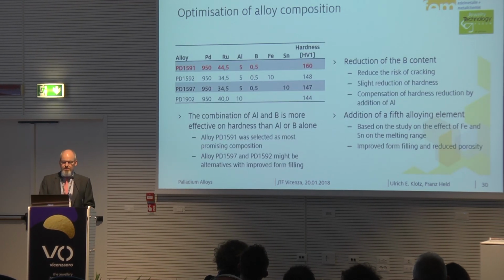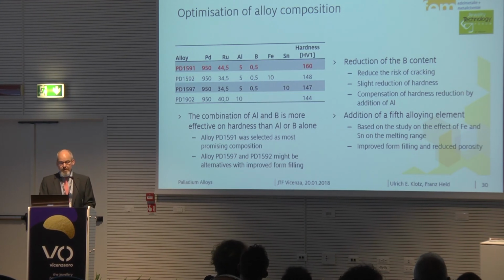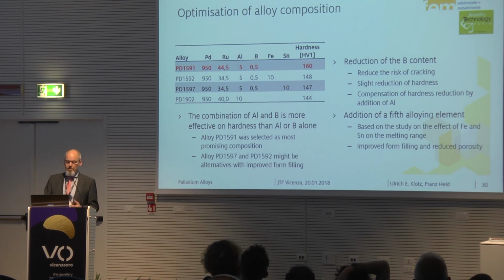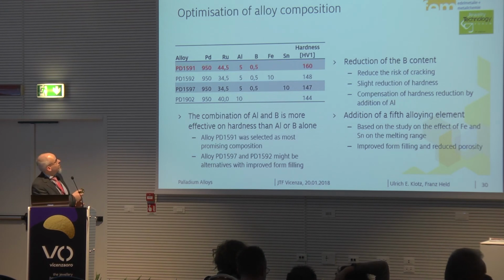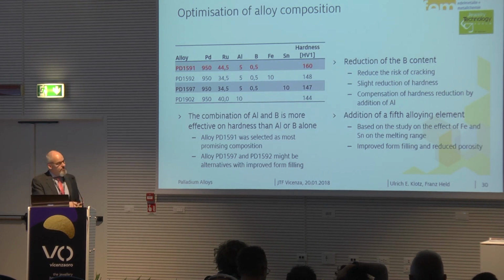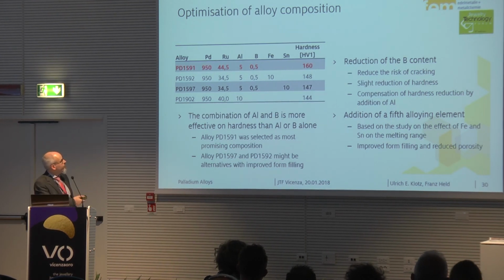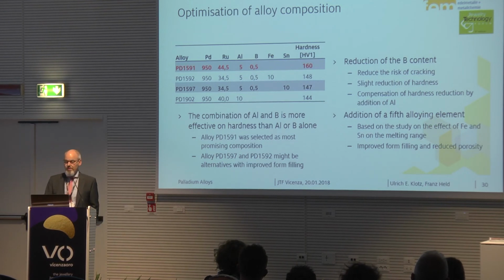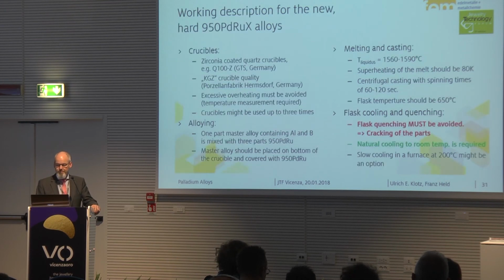Then after some more iterations, we came up with 4 compositions that we found are very promising, and we found that the combination of boron and aluminum is quite beneficial, and that we don't need very high additions to get into the desired melting range. Iron is beneficial for grain refinement. Tin is beneficial for increasing the melting range. And so these were 4 compositions which were promising, which met the objectives of the alloys we wanted.